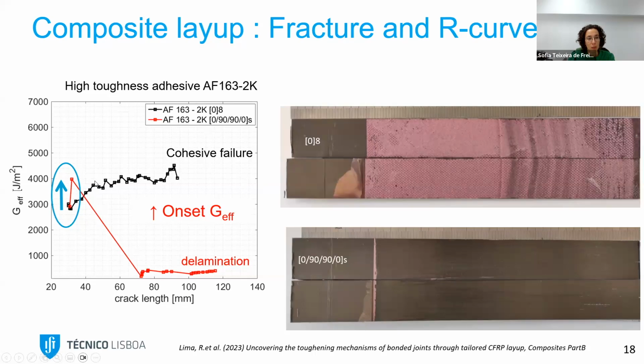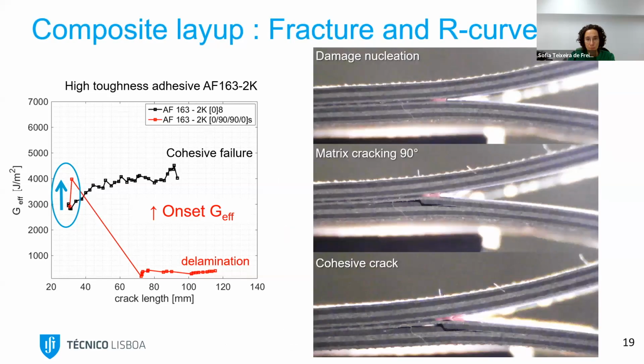So we tried to look a little bit more into our pictures from the microscope that we were using to look at the test. And what we saw was that in the beginning, we see a little bit of damage nucleation in the adhesive. And then we see 2 types of cracks. A primary crack, which is in the adhesive, but we also see a secondary crack, which is in the 90 degrees matrix cracking inside the composite. So because we have these 2 cracks happening at the same time in the joint, we again trigger this crack competition between the 2. So the energy that we are imposing in the specimen is being divided between 2 fracture surfaces, one in the adhesive and another in the composite. And this is why we see this increase in the fracture energy. So that was explained.